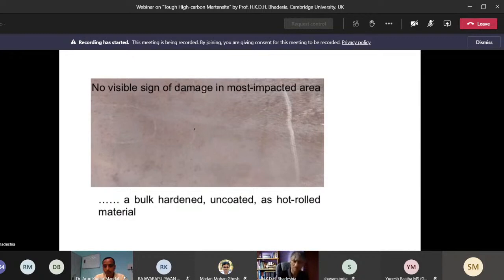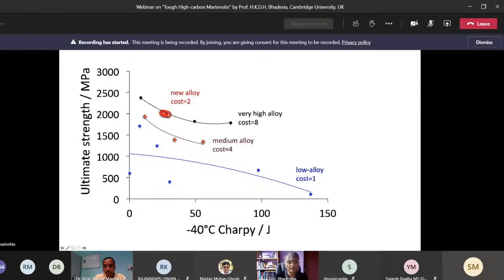Now, one other example why this steel is likely to be very successful is that, look, if I look at the strength versus the Charpy plot, these are sort of ordinary low alloy steels. And if we label the cost of ordinary low alloy steels as 1, a medium alloy steel with a strength approaching 2 gigapascals will have a cost of 4.